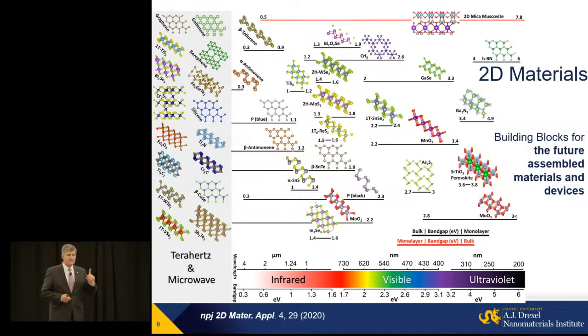Keep in mind that graphene, which is often praised for its conductivity, is a zero bandgap semiconductor. You have to either dope it and create defects to create carriers. In the majority of MXenes, you have very good metallic conductivity, even with surface termination. In graphene, you get graphene oxide, for example, or hydrogen-terminated graphene, and conductivity drops by 6-7 orders of magnitude. You basically kill it here.